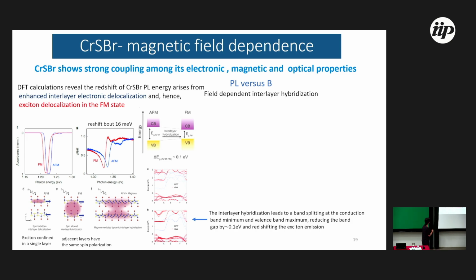The main qualitative explanation is this: when you shine light, you have the exciton in one layer, and you cannot have diffusion because the spin in the next layer is different. When you have the phase transition to ferromagnetic, you can have interlayer hybridization, because you can have diffusion of electrons from one layer to another. This hybridization, which occurs in the ferromagnetic phase, changes the band structure, which is easier to see here.